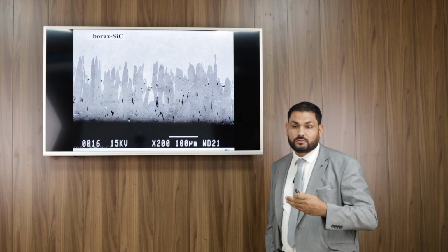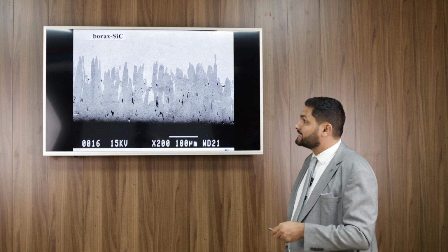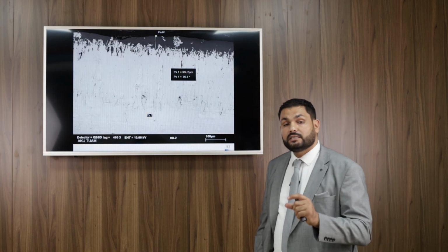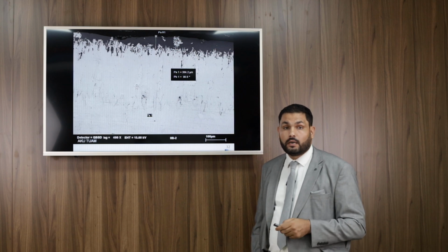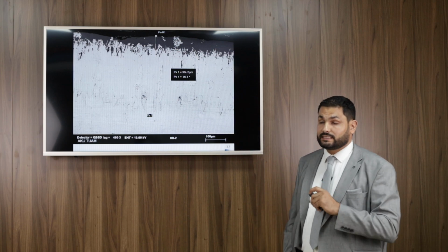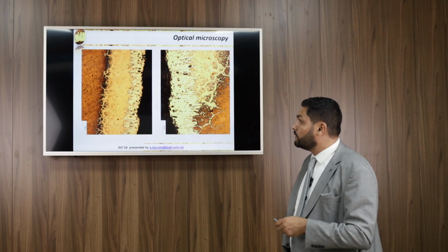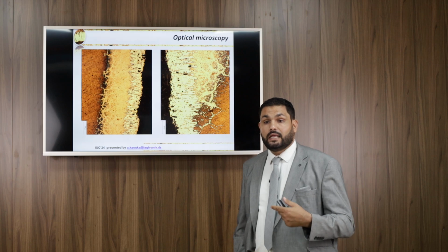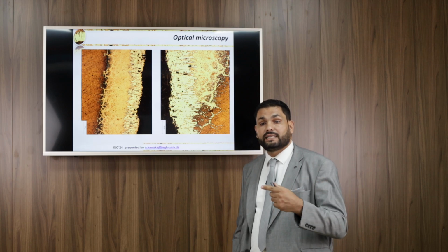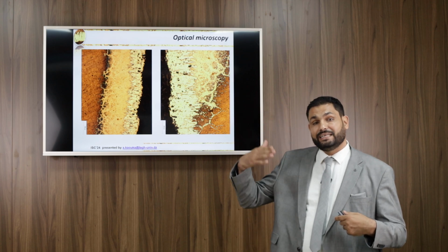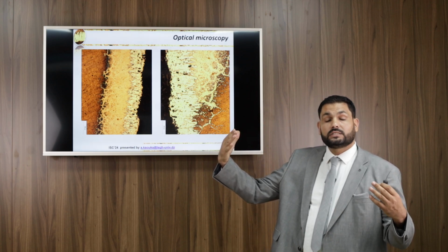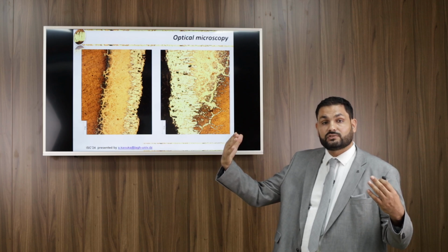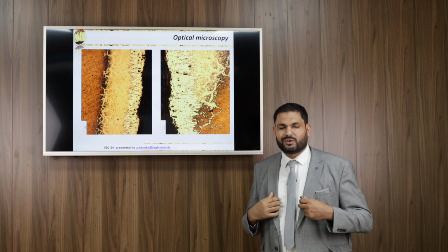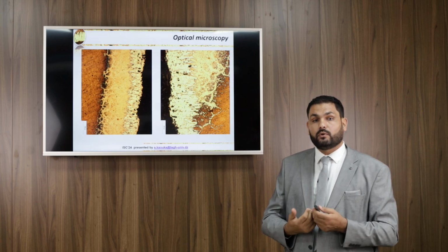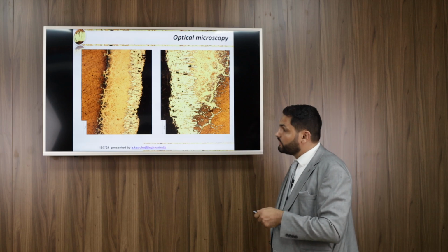Even when we increase temperature and increase the time, we always have monophase. And the thickness of boride layers can be attained until 384 micrometer, and this is a very interesting thickness. We also measure the thickness of boride layers, and we studied the kinetics of boride layers formed. We found that when we increase the temperature, there is an increase of thickness of boride layers formed on substrate. However, there is more or less increase when we increase the time of the boriding process. So we measure the thickness of boride layers.